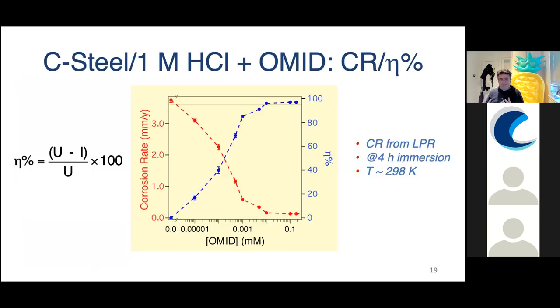So let's look a bit more quantitatively now at how well this molecule is working. Here, what I'm plotting is corrosion rate on the left-hand side, and on the right-hand side, the inhibition efficiency, which goes between 0 and 100%. We've measured the corrosion rate from LPR, linear polarization resistance, with the immersion and temperature conditions as per the last slide. You can see the corrosion rate goes down, asymptotically towards zero. Of course, the inhibition efficiency is the mirror of that, and it's going upwards towards 100%.